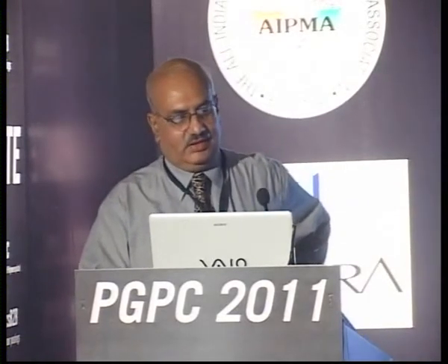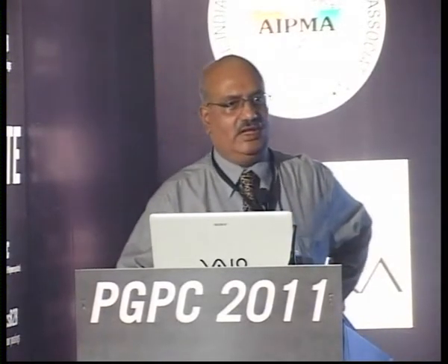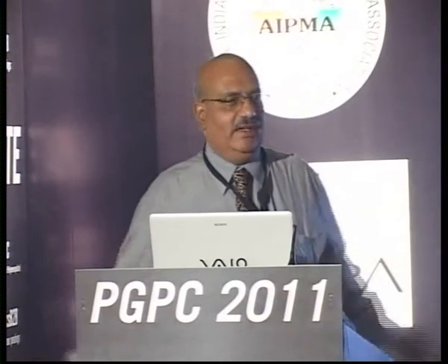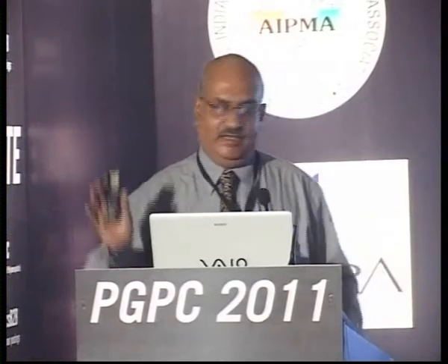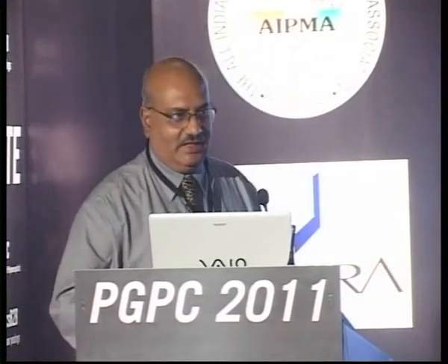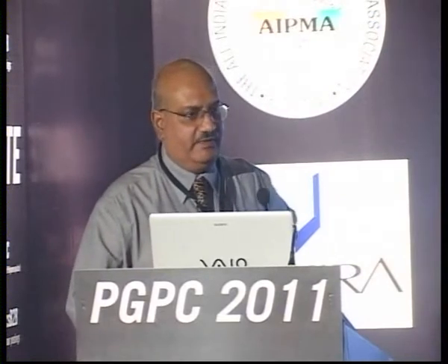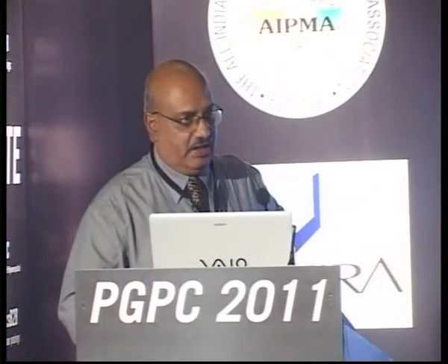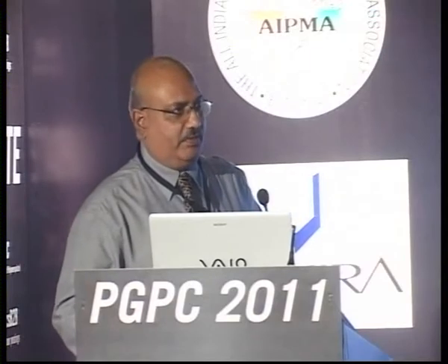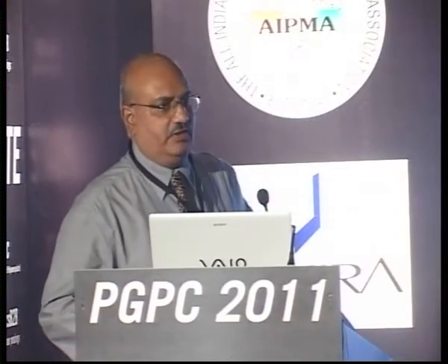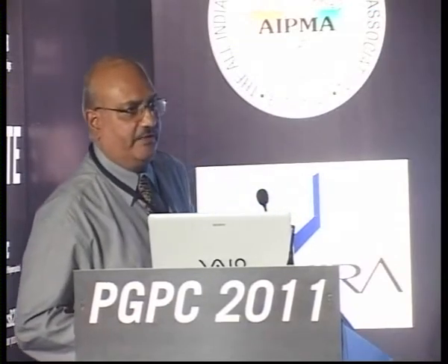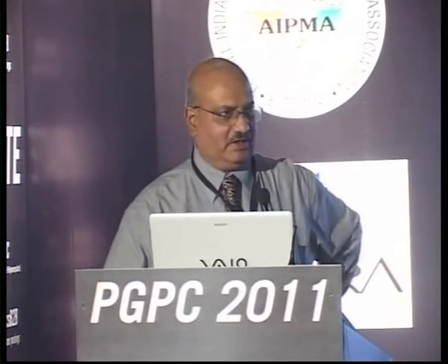Color tolerances. This is a subject close to the heart of these auto guys, you know. They think that once they've got 0.5 delta E, they've solved all their problems. That is not the case, but still for good form, we can make the master batch to 0.5 delta E, but we ensure that despite being 0.5 delta E, it is a good visual match. Because 0.5 is not the same thing as good visual match. It's a good start for a good visual match, but it is not a good visual match.